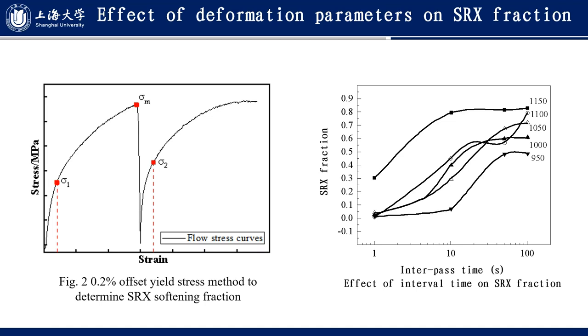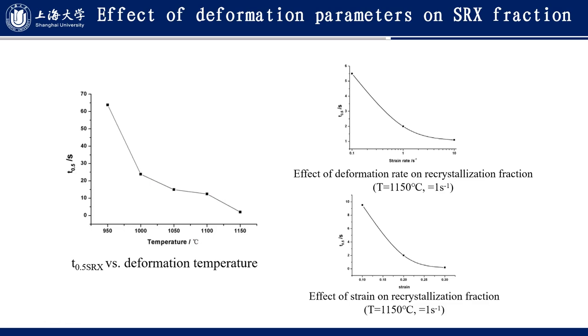The softening fraction of static recrystallization is determined by the 0.2% offset yield stress method, according to this figure. And the recrystallization fraction is calculated according to this equation. This is the result of the relationship between interpass time and static recrystallization fraction. And the 50% static recrystallization time versus deformation temperature, the effect of deformation rate on recrystallization fraction, and the effect of strain amount on recrystallization fraction are obtained.